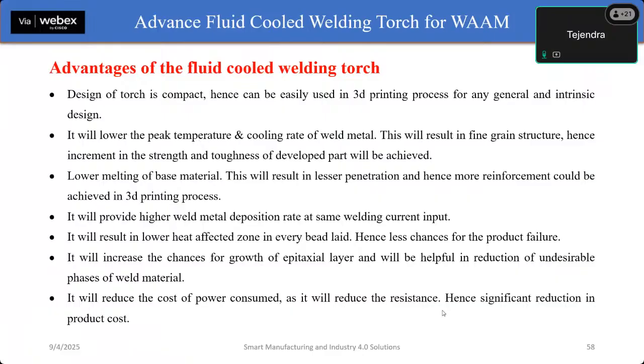Lower melting of the base plate: as we know in the MIG process, 66% of the current goes into the torch and 33% goes into the substrate plate. If we are reducing the current requirement from the primary welding source, that means the 33% current will also get reduced. Hence, a lower amount of current goes into the plates. That means lower melting of the base material, which will result in lesser penetration and more reinforcement can be achieved in our process.